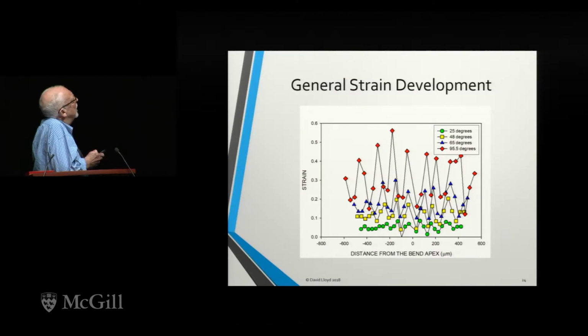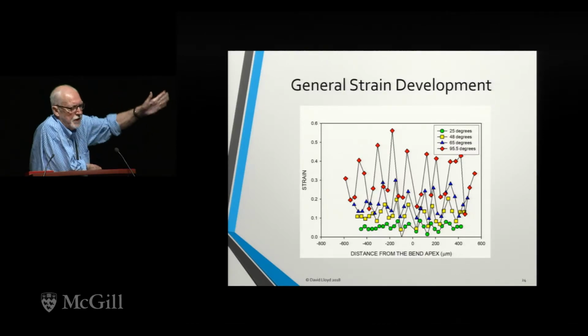It goes up to there, and then when you say it goes up, continue bending, it goes even higher. So localization starts very early on. And this is not differentiating whether I'm at a boundary or anywhere else, really. We're looking, as you can see, across a region of about 600 microns either side of the bend apex, which is at the 0 point. So the deformation localizes early and concentrates early.